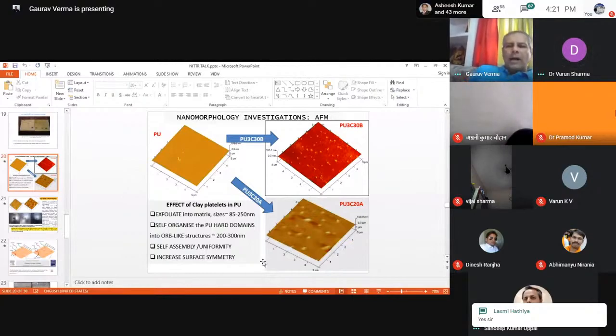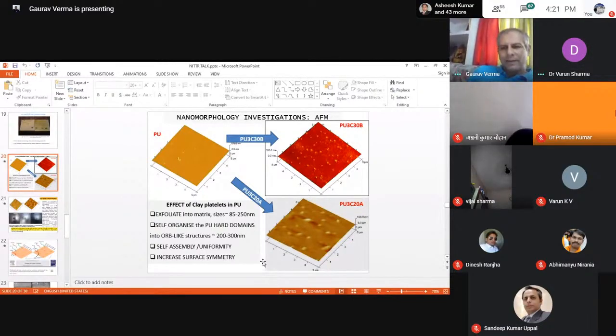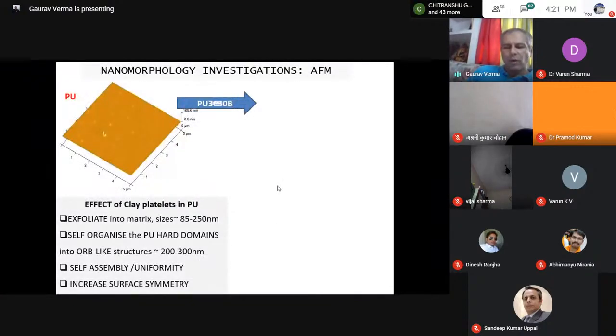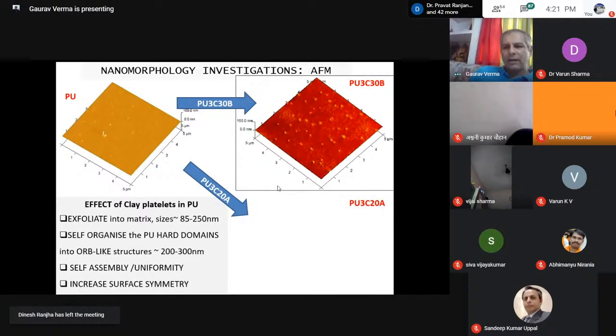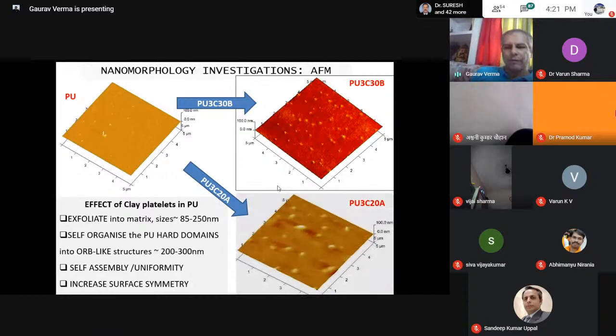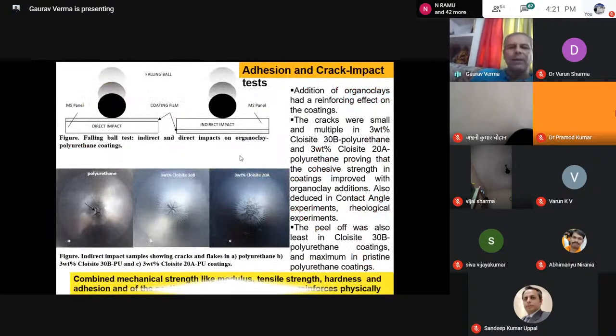Okay. So this actually is the real crux of the problem, because here we are looking at the automotive coating, which has been modified into a nanocomposite coating, and the symmetry which you see on the surface of these coatings, which can be investigated by atomic force microscopy. You would understand that the symmetry and the nanomorphology we create on a pristine polyurethane coating will result in better properties. And I was just trying to explain that example.